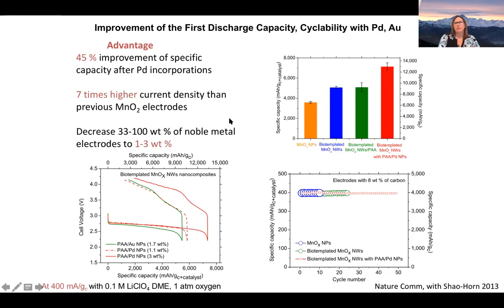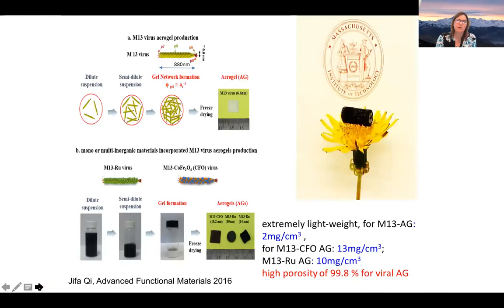And so this graph over here is looking at specific capacity versus different ways that we synthesized it. If you look at the manganese oxide materials by themselves versus templated biologically versus doing them both with the palladium and the biotemplated manganese oxide, we got the best materials. And it was state of the art at the time we published it for these types of materials. And then we went off and explored many different kinds of materials using the same kinds of technologies.